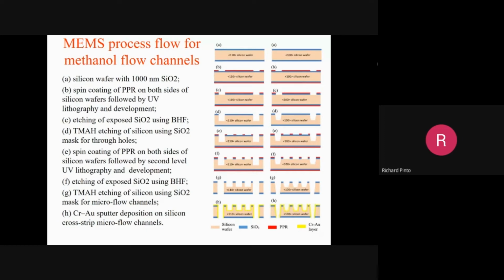Okay, this is G. And H is where you need to deposit a thin layer of metal to get the current, the electrons, out into the external circuit. That's why you need a thin layer of metal, because silicon itself is not a very good conductor. So you need a thin layer of metal to get the power output from the cell. So this is the basic schematic.